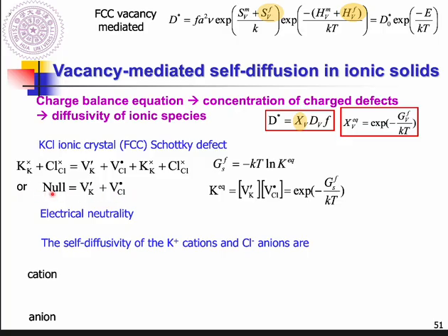Before, there's no Schottky defect, then we form a pair of positive and negative vacancies: a pair of potassium vacancy at the potassium side with a negative charge, and also the vacancy at the chloride side with positive charge. So it will be the pair of vacancy.